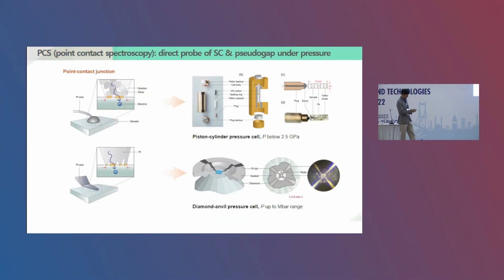So experimentally, we used two types of pressure cell to do point-contact measurement under pressure. The first is a piston-type cylinder cell, which we used below 2.5 GPa. And then we also used a so-called diamond anvil cell, with which you can measure ideally up to the megabar range.